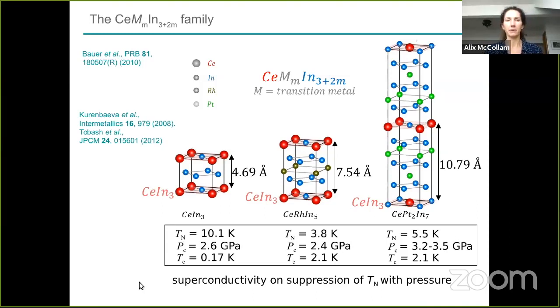But what happens with high magnetic field is a question that hasn't really been answered very clearly, at least not uniformly across this series of materials. So the Néel temperatures are relatively comparable. They're all antiferromagnetic at ambient pressure and at zero field. When you apply pressure, you get superconductivity appearing at comparable pressures in each case. And then TC is much lower for cerium indium-3, and it's comparable here for these two systems.